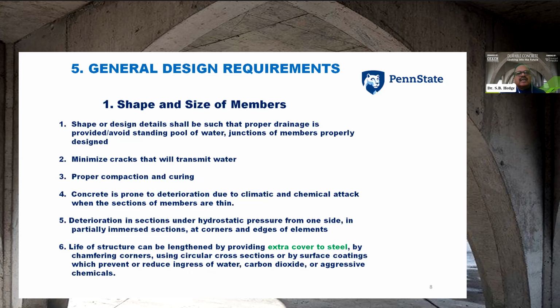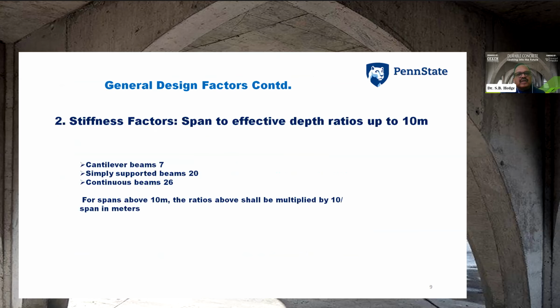If you see the general design requirements, the shape or design details shall be such that proper drainage is provided, avoiding standing pools of water, with junctions of members properly designed. Second, minimize cracks that will transmit water. Third, proper compaction and curing. Fourth, concrete is prone to deterioration due to climatic and chemical attack, deterioration in sections under hydrostatic pressure from one side, and partially immersed sections at corners and edges of the elements. So these are certain design things that have been considered.